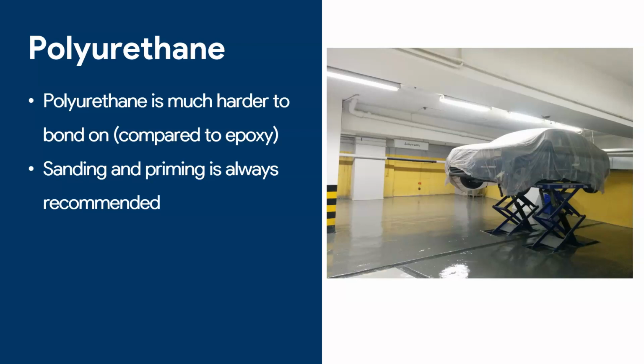So that's why I always recommend, if you need to apply epoxy on top of polyurethane, always do a quick sanding first and prime the surface to make sure that it will stick properly. I have seen cases where the epoxy starts to peel off polyurethane, so you want to be careful with polyurethane.